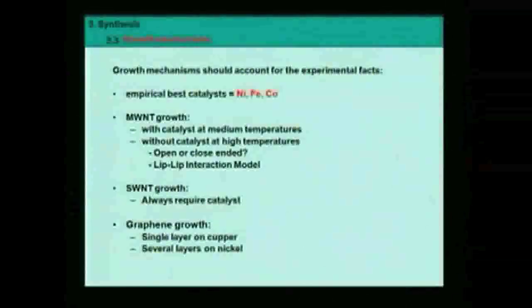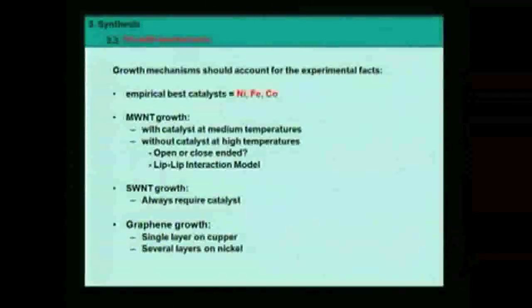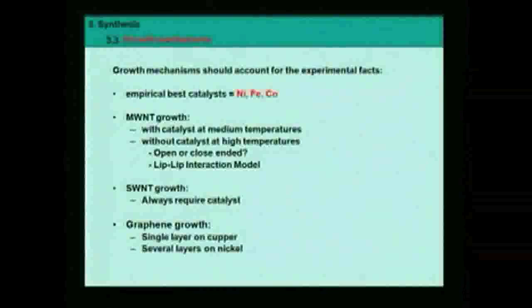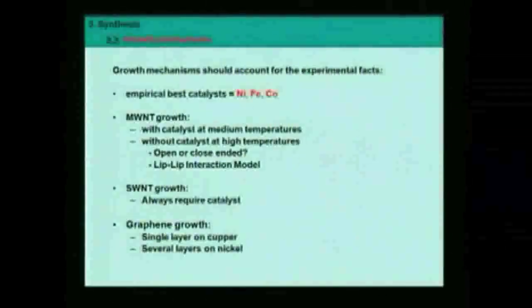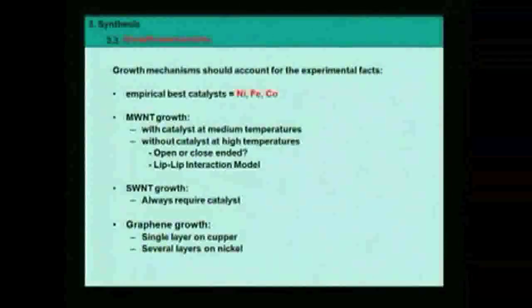Then for multi-wall nanotube growth, you can grow them with catalysts at medium temperatures, but the interesting thing is when you use high temperature methods, you do not need a catalyst. Why is that? You need to answer this question. For SWNT growth, SWNT is single wall nanotube, you need a catalyst in any case. Why is that? For graphene growth, there is also an effect of the catalyst on the number of layers, and you may wonder also why is that. So we are going to try to answer those questions by an appropriate mechanism.